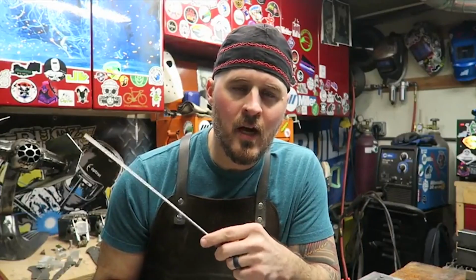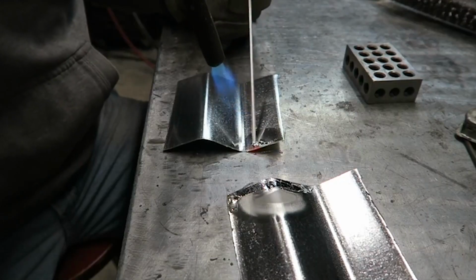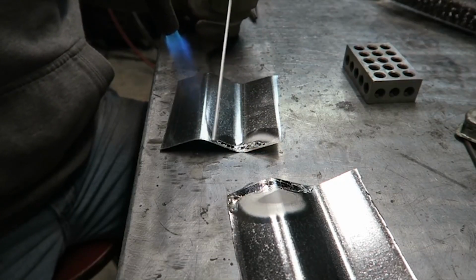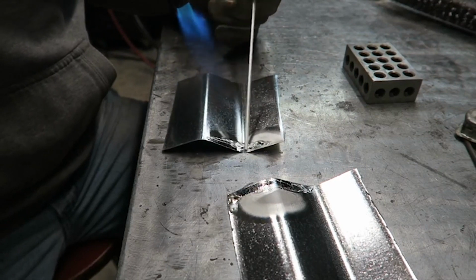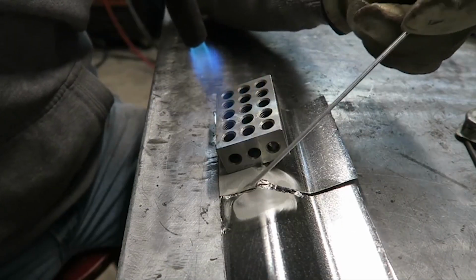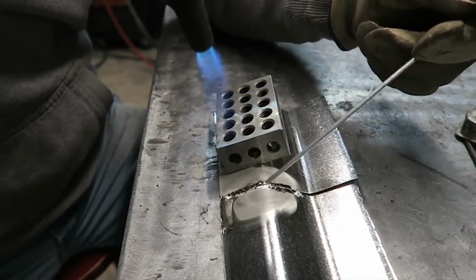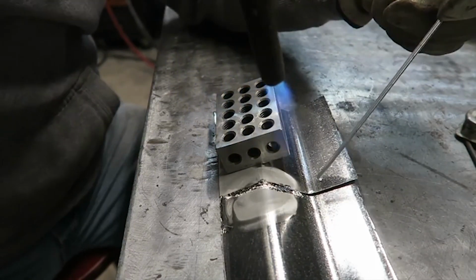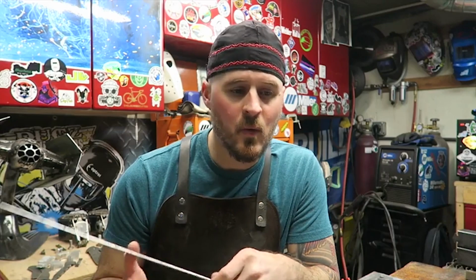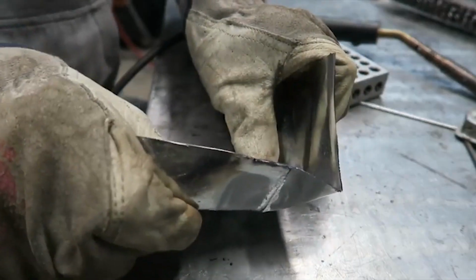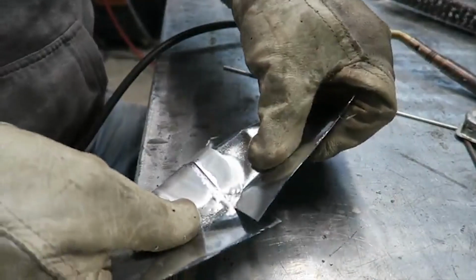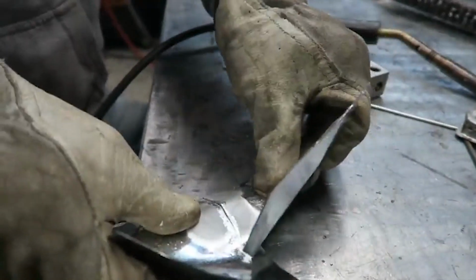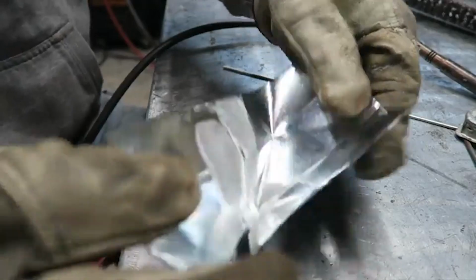For this last demonstration, I will solder 2 thin pieces of galvanized sheet metal together with this rod using no flux. Same principle as before. Clean the base metal, apply gentle heat, and then tin both surfaces. Once the surfaces are tinned, lay them on top of each other. Apply more heat until things are molten, and then you can even build up a small fillet at the joint area. Once everything cools off and solidifies, you will see that the joint is quite strong and will actually pull the galvanized coating off of the steel before it fails.